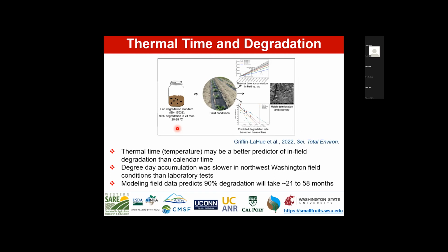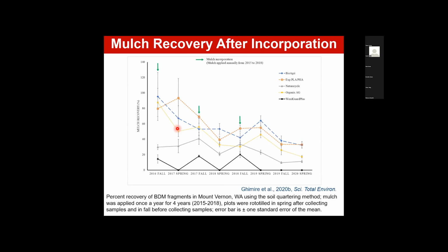So the other thing I'd like to highlight from this same field study or same field site, but a different paper, is that the mulch films and the biodegradable mulches that were used in this study were degrading over time. So even though we have longer time that it takes to degrade based on this work because of thermal time accumulation, these films are still degrading in the environment, as we can see in this figure here published in another paper. So what we're looking at here is percent mulch recovery. This is from fall 2016 to spring 2020.